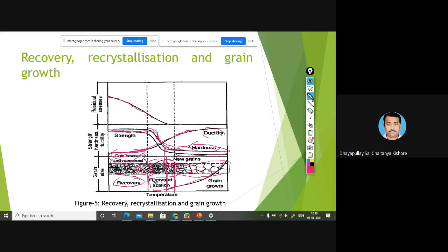Especially, the residual stresses will be reduced by increasing the temperature. During recovery it is reducing, and after that, with further increase in temperature, these values decrease completely. The leftover locked stresses will be reduced due to the increase in temperature. You can observe that the residual stresses become zero here. Once you increase the temperature over the recrystallization temperature, it completely relieves the entire residual stresses. So that is about recovery, recrystallization, and the grain growth zone, where even at the end of the recrystallization zone, the grain size starts to increase.